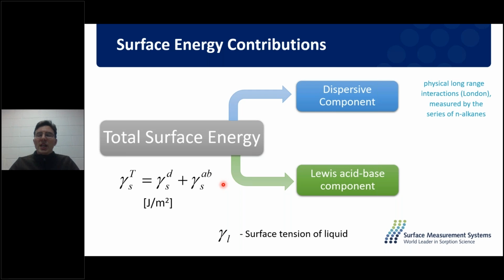So by using our non-polar probes, our hexane, our heptane, our undecane, our decane, these are probes which have no polarity. They will only interact with our surface as a result of van der Waals and London forces. So it's these induced dipoles that are the reason that we're interacting with our surface. So this is how we calculate our dispersive surface energy. It's by calculating that van der Waals contribution that's resulting in the activity of that surface.